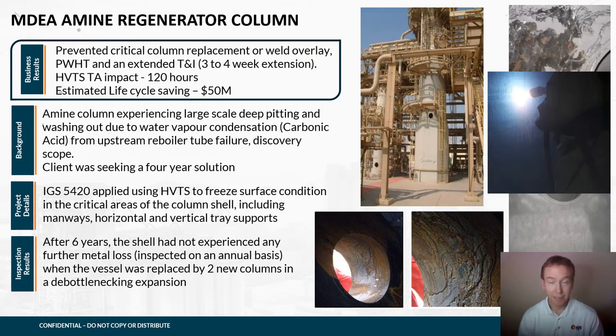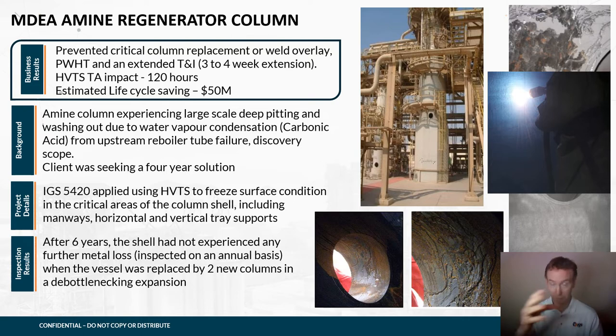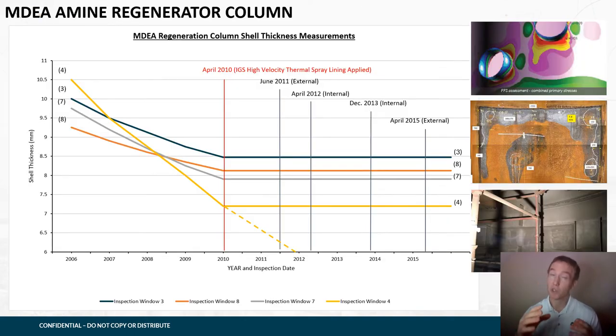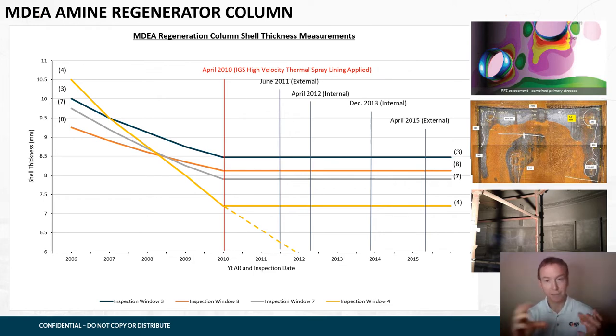This second example is slightly different. In this case, a failure upstream of the column led to condensate getting into the middle section and creating very aggressive carbonic acid corrosion. This was found as a discovery scope during a turnaround. To repair it with welding, the client would have had to stabilize the vessel, loosen all the bolts, do the welding, and carry out post-weld heat treatment — extending their shutdown by probably three to four weeks. IGS was available to come to site immediately, and we completed the application protecting this area in nine to ten days. After the application, internal and external inspections confirmed no change in wall thickness, protecting the areas that were already at minimum wall.